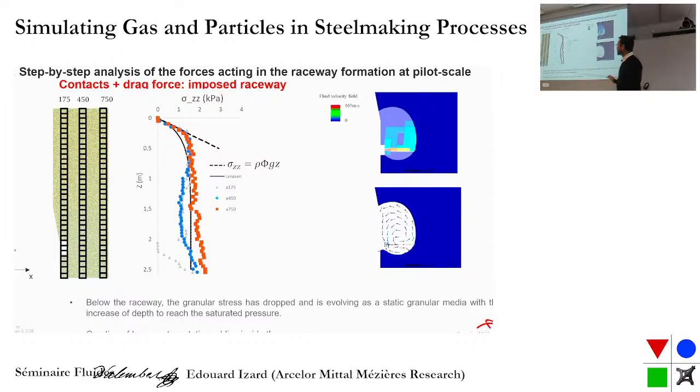What you can observe is that the granular material is experiencing a Janssen effect where the pressure saturates because the pilot is very narrow, so the forces are distributed toward the wall.